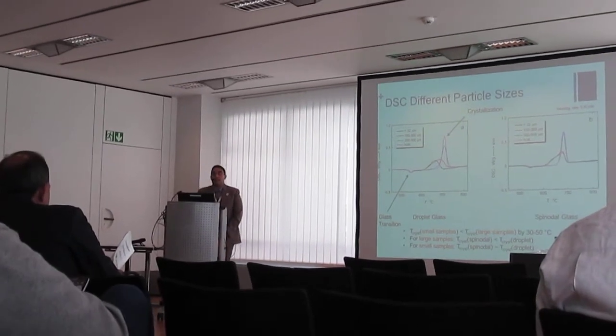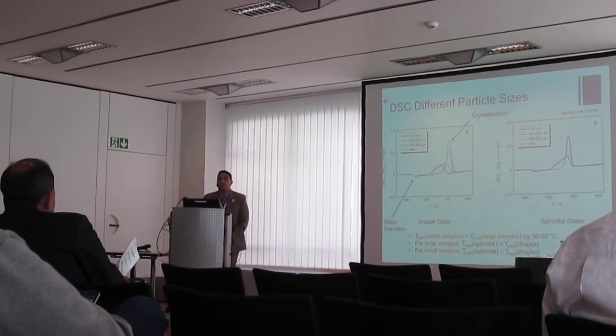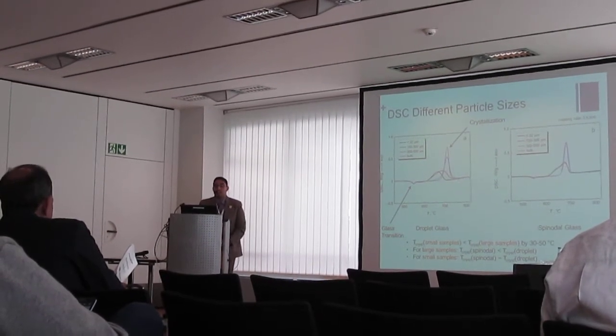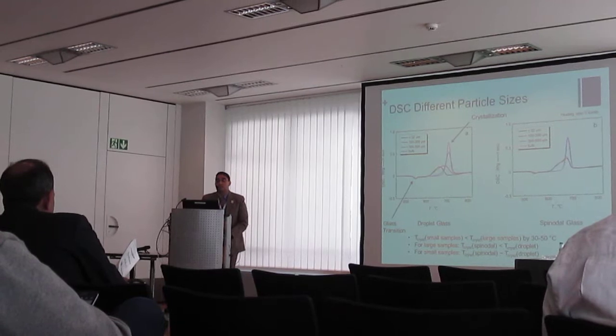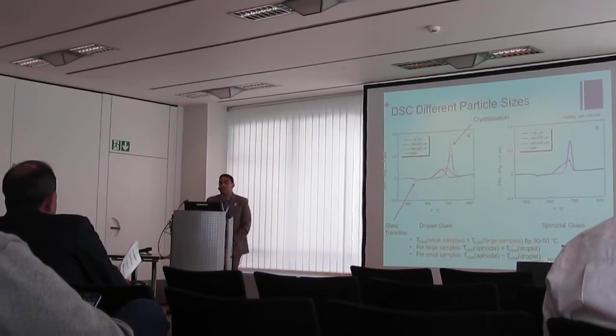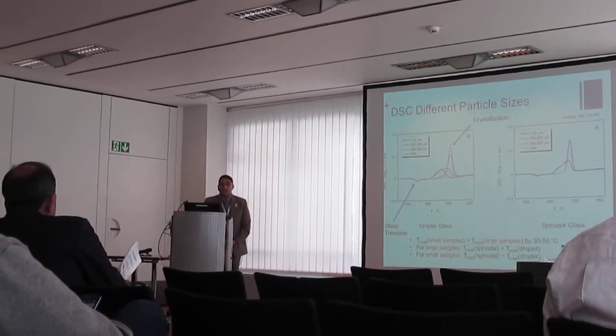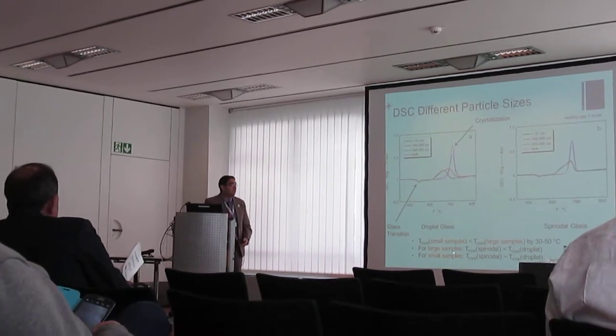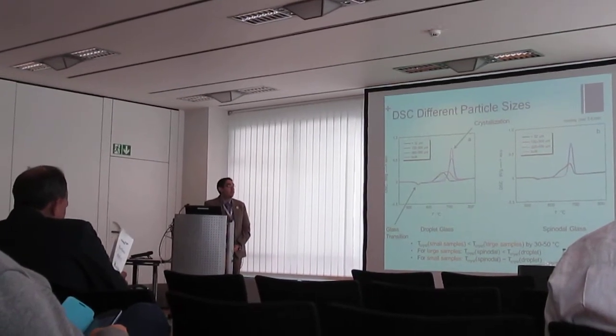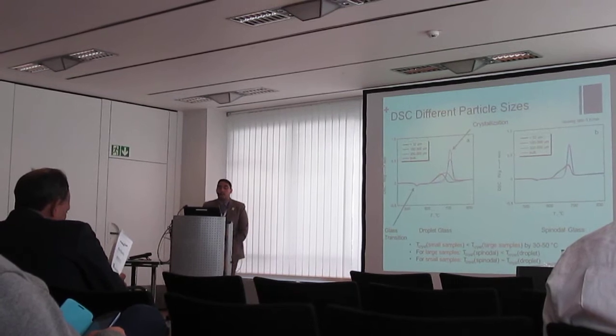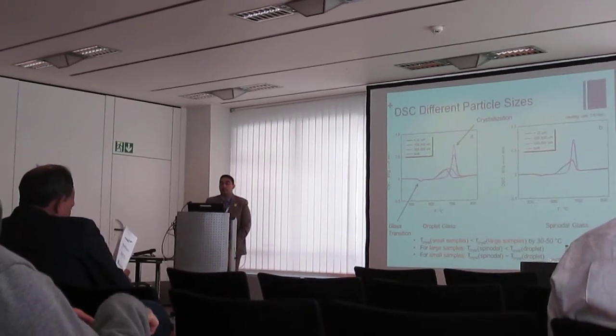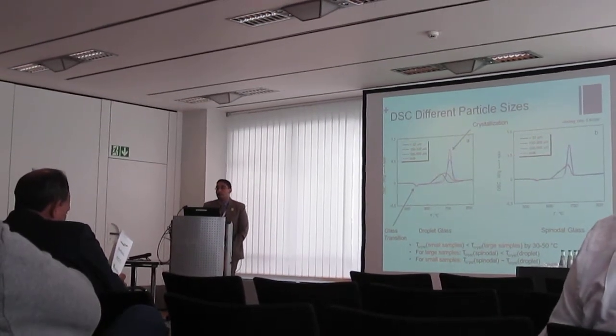We also see that for the larger samples, the 300 to 500 micron and the bulk glass, the temperature of crystallization for the spinodal glass is less than that for the droplet glass. Similarly, for the smaller samples, 32 micron and 150 micron, the onset of crystallization is about the same for both types of glasses.